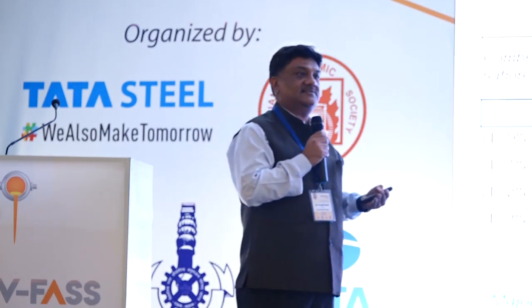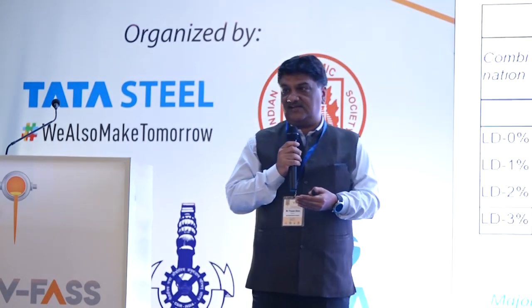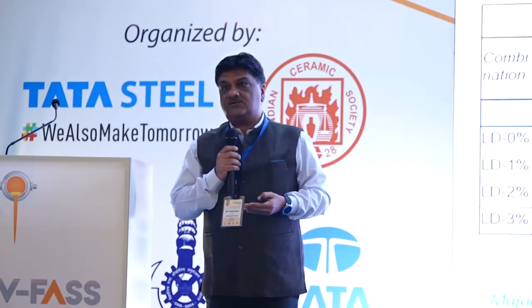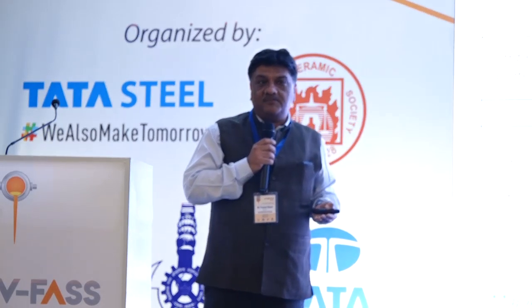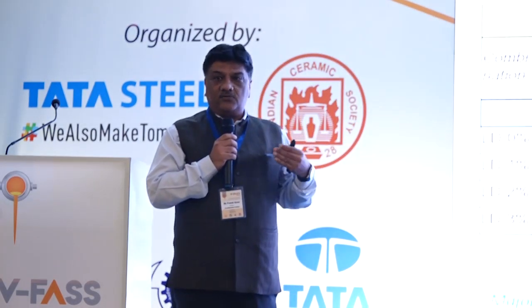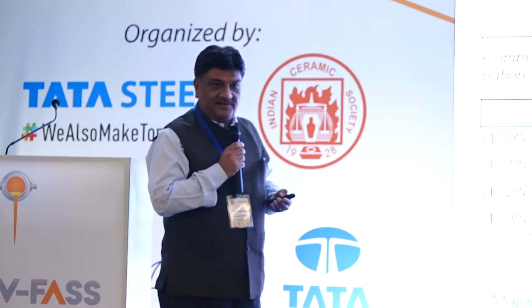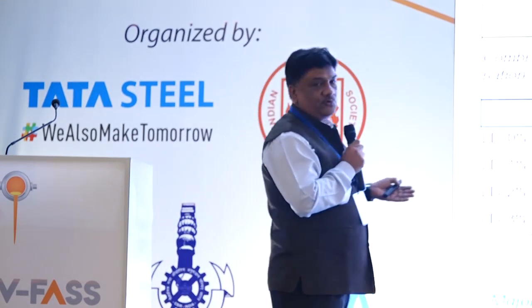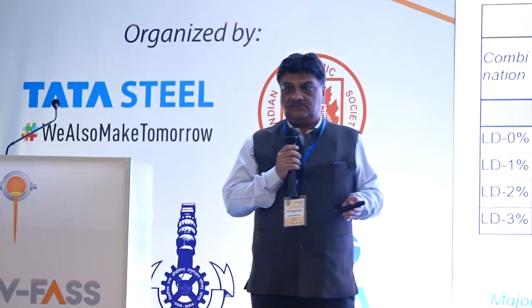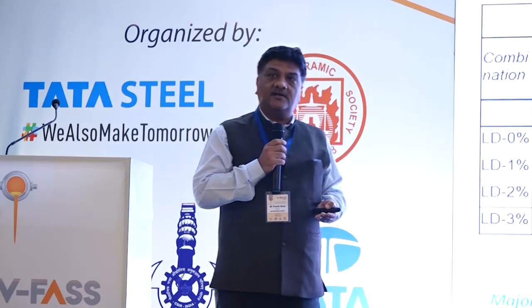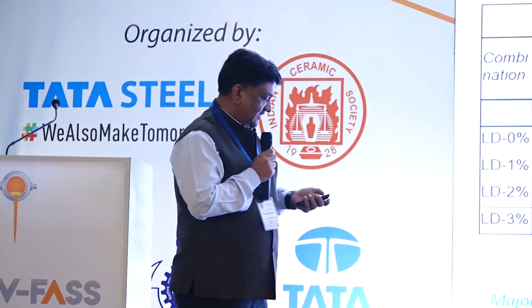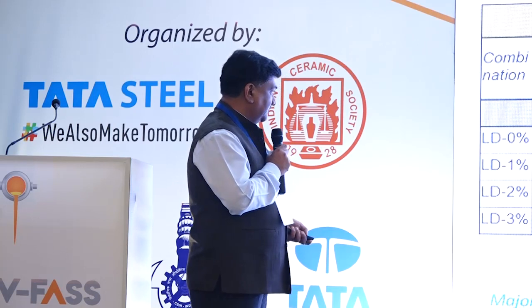Though we are saying that there are some processes which have been adopted even at TSL level, that has gone up to only 10 to 15% glass content. We have done some crude method, which I am not revealing today, but we could improve it to 60, 67%. So further study is required on how we can improve the glass content in the LD slag.